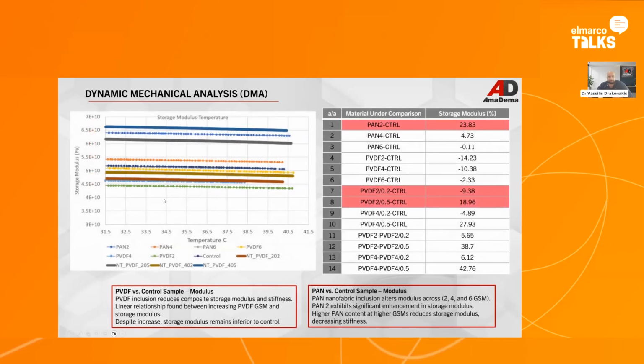So here you can see how the control is the blue line, and then how we go with the PAN without nanoparticles, sorry, the PAN 2, 4, and 6 in different concentrations, going above, let's say, the control. The PVDF, because it's a different polymer, goes a bit below, but gives a better toughness overall. And then we see how the nanotubes within the PVDF increase compared to the PVDF alone and go beyond also the control. And this is the storage modulus at, let's say, around 35 degrees Celsius.